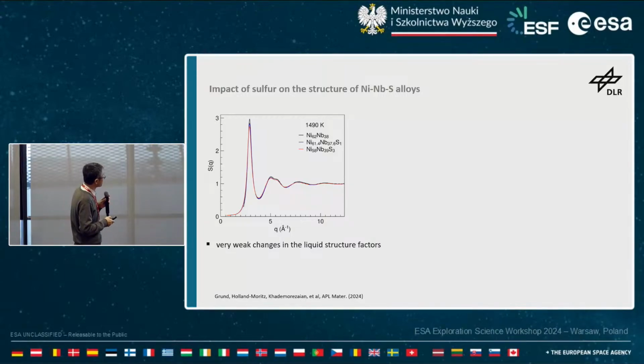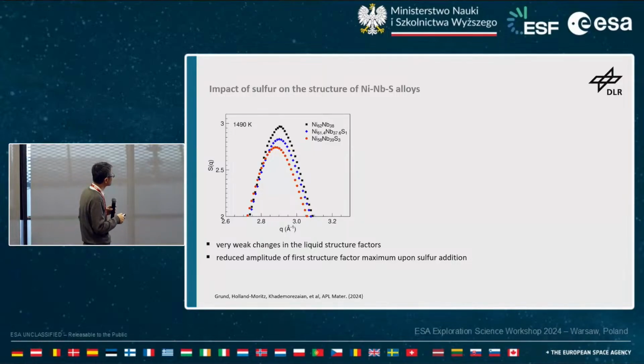We look at the structure also. This is also a very small change, but here we do see that the structure changes more. What you can see is this is in the melt, and this part, the first sharp diffraction peak, is decreased in amplitude. If one looks at it carefully, the position also changes a bit. So there are structure changes in this melt upon sulfur addition.